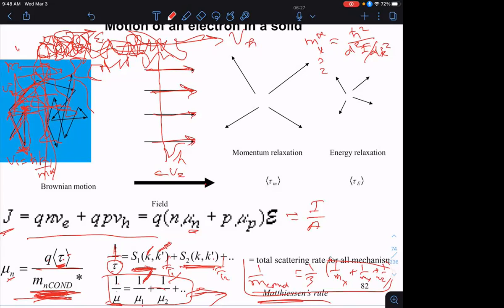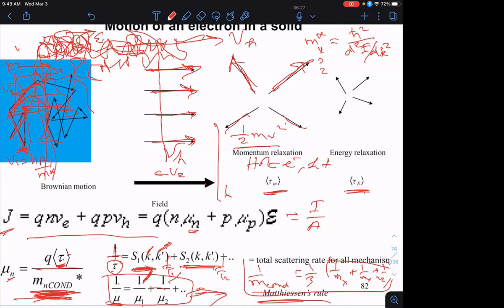Now, what ends up happening, and this is not something that you'll be tested on in the class, is if after time t you get rid of the electric field, because of these collisional events, pretty rapidly these well-directed velocity vectors will get randomized again. That characteristic time is known as the momentum relaxation time. But for a few nanoseconds or picoseconds, the magnitude of these vectors are still pretty long, meaning that the kinetic energy, half m v squared, is still very, very high. These electrons or holes are now called hot electrons or hot holes, meaning highly energetic electrons or holes. It takes another characteristic time constant, known as the energy relaxation time, for them to cool down to the ambient temperature.